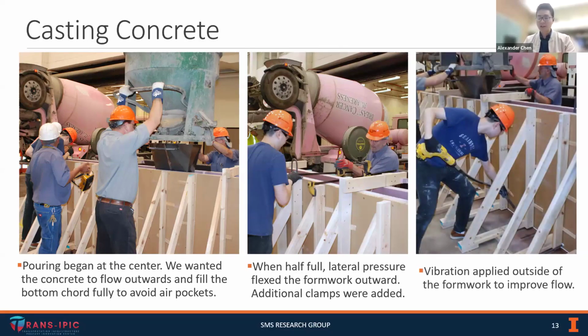And because of the rebar congestion, we weren't able to put the vibrator into the concrete to remove air bubbles. Instead, what we had to do was use the vibrators externally and vibrate the formwork.